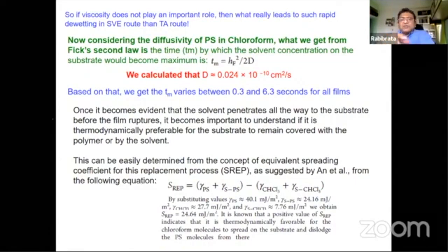And we took from the literature or calculated the value of D. And based on that, we saw that for the type of films we are looking at, based on their thickness variation, the TM varies between 0.3 to 6.3 seconds. And you are talking about even in solvent vapor dewetting, timeline of dewetting to be of the order of minutes. So as soon as you start your experiment, almost in no time the solvent vapor reaches the substrate, right? So this is what was happening.